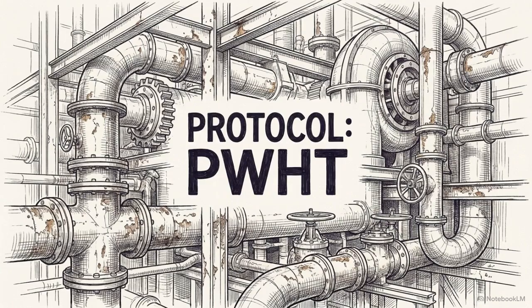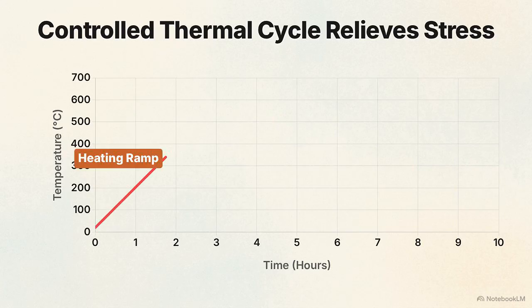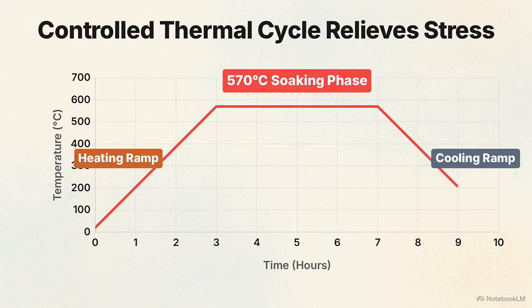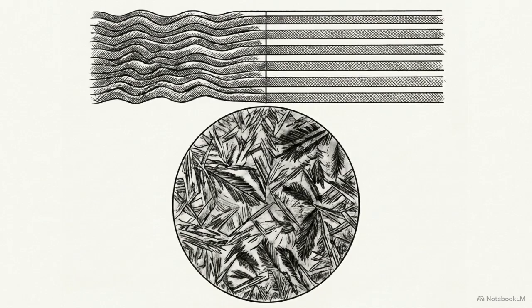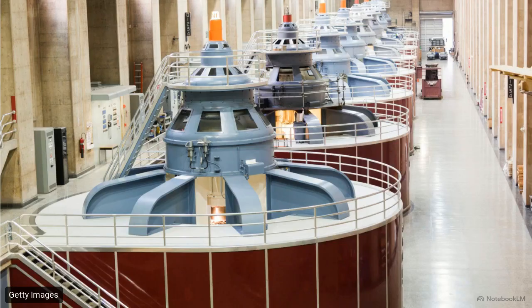The second mandate is rigorous post-weld heat treatment. To be effective, this treatment requires controlled heating and cooling ramp rates. This relaxes localized tensile peaks without compromising the required bainite microstructure. Accurate modeling of non-symmetric thermal stresses is the only reliable way to guarantee the real-world lifespan of critical power generation infrastructure.